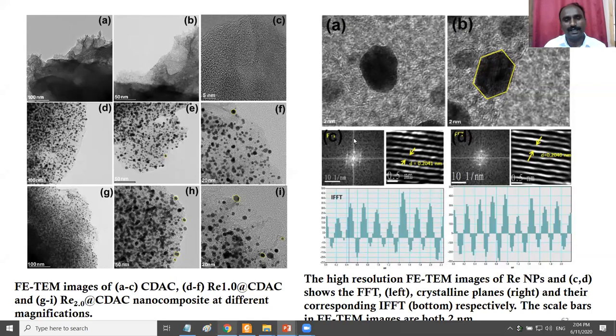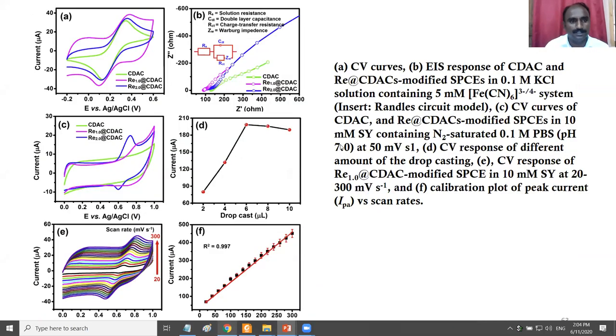After characterization, we go on to the electrochemical studies. Cyclic voltammetry is used to study the current values. The lower one is the CDAC, the carbon material only. After doping with rhenium, the current value increases somewhat. That means the conductivity is higher than the bare carbon material.